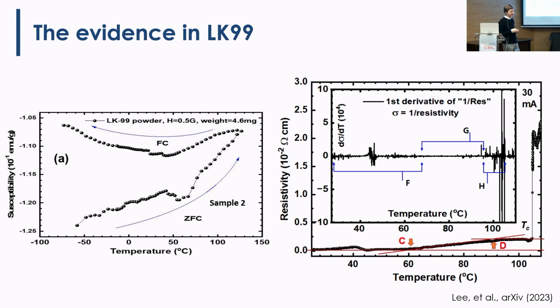It's fantastic. But still, if you look at the data, the resistivity here is huge. This is much bigger than the resistivity of copper, much, much bigger. But still, they will say, okay, maybe you have impurities in the sample. If your sample is not pure enough, or the connection through the electrodes is not going through a superconductor, you will have a residual resistivity.